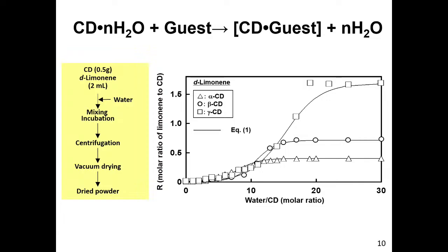We prepared 0.5 gram of the powder, cyclodextrin, and then D-limonene, plus added 2 milliliters and a small amount of water. After incubation, centrifugation, and vacuum drying, we can get the dried powder. We measure the content of the D-limonene.